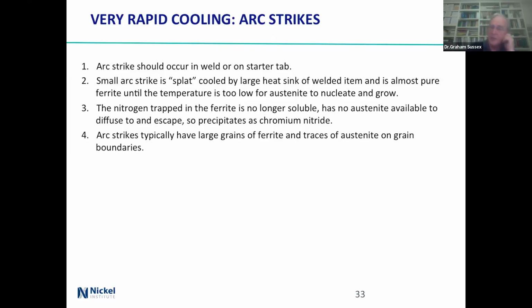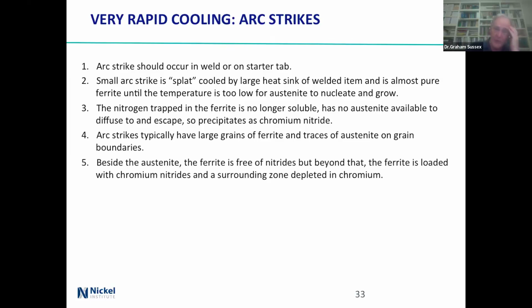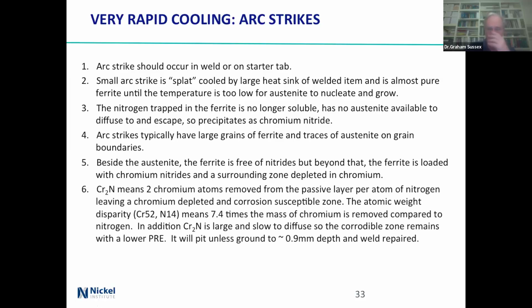Typically, if you look at an arc strike, it's got big grains of ferrite, traces of austenite on the grain boundaries, and that's about it. The ferrite doesn't have much in the way of nitrides right up close beside the austenite, but if you go away from the austenite, then it's loaded up with chromium nitrides, and the surrounding zone is depleted of chromium simply because the nitrides have taken out the chromium. And so instead of being chromium oxide, it's chromium nitride. And here's the sums. Cr2N, two chromium atoms per atom of nitrogen. So you get a chromium depleted and corrosion susceptible zone.